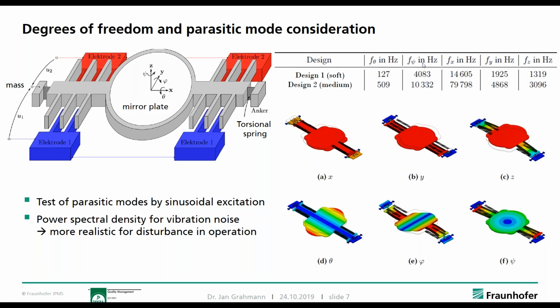And then you have further frequencies that represent eigenmodes of that mechanical system shown here on the left side. And these mode shapes, so how the scanner oscillates parasitically connected to these frequencies, are shown here below. And that is of course also true for design 2, but here the difference is that the first resonance frequency is quite a bit higher, at about 509 Hertz, and the other parasitic frequencies also go up in frequency.